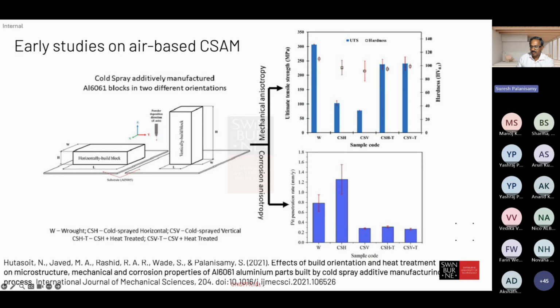Corrosion properties are far better with regard to the heat treated conditions. Cold spray parts that are heat treated are close to the wrought material conditions. That's what I should say. The as-built is close to the casting properties. What we can achieve is the casting properties. So you're looking at the replacing of some of the casting parts.